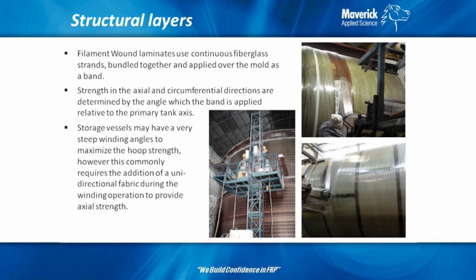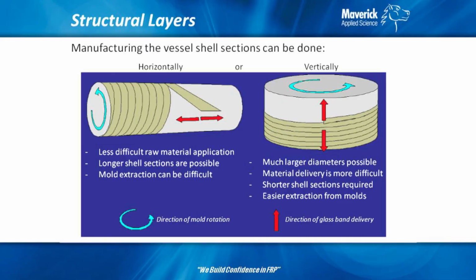You can set the strength of a pipe or a tank based on the wind angle. On a pipe, we were always taught a typical perfect wind angle is 54.7 degrees, and that optimizes the strength in the circumferential direction and the axial direction. So for a piece of pipe, you want burst and you want axial strength. On a storage tank that's atmospheric, you don't need as much axial strength, so you'll typically see steeper winding, say 70 degrees or something like that, to match the circumferential strength you need.